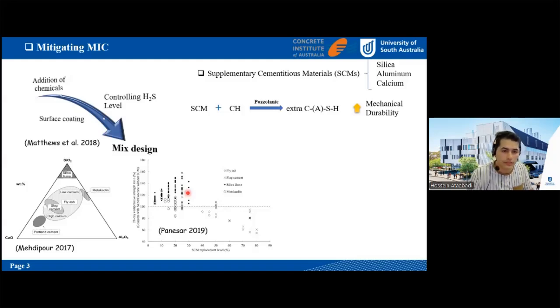For improving the mix designs, different supplementary cementitious materials have been included in the mix design of the concrete. As you know, SCMs have a lot of silica, aluminum, and calcium in the matrix, so they can react with the hydration products of the cementitious material and produce extra gel, calcium aluminum silicate hydrate gels, that can improve the mechanical and durability properties of the concrete as well.